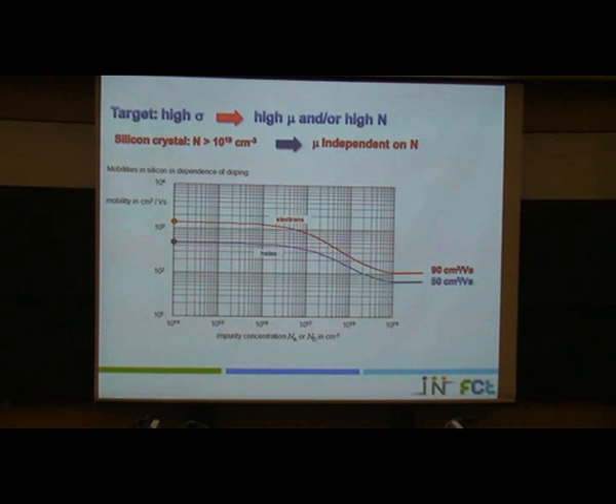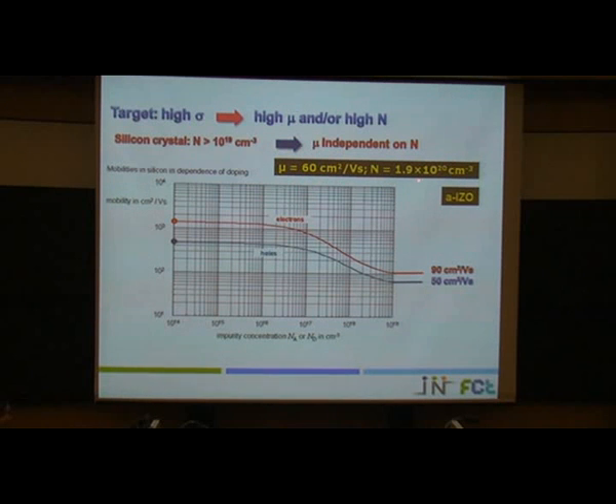per volt per second. And for example, we can produce TCOs or oxide semiconductors with very high values of mobility, around 60, and with a high carrier concentration. But we can produce this type of material at room temperature. So this is a huge advantage for this type of oxides. Even if we compare these materials with silicon, and this is monocrystalline silicon, this is the typical graph that we use in microelectronics to calculate the resistivity as a function of the doping or impurity concentration. And we achieved these values, for example, for amorphous indium zinc oxide films.